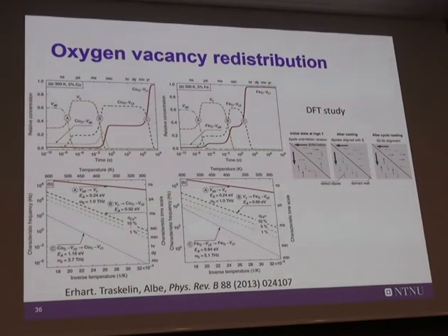If you look at this data, look at the concentrations here, that's the important thing. In the beginning, the material is dominated by the oxygen vacancies in the AB plane, which have a much higher concentration than on the C, and that's naturally because of statistics. The first relaxation happening is that the vacancy moves to the VC position, because that's energetically more favorable. And then you see that the dominating species is this free oxygen vacancy.